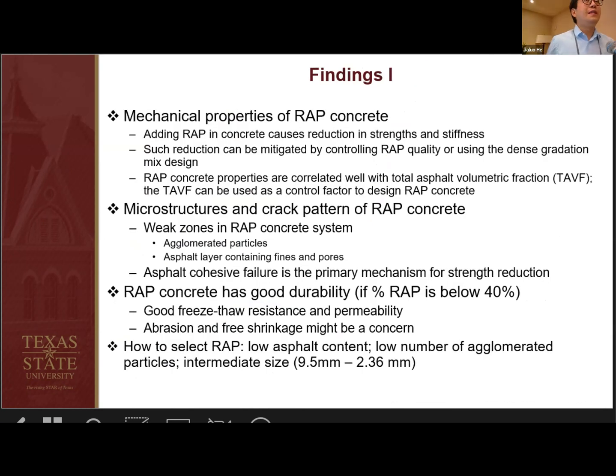Like I said, I skipped a lot of details. I just want to conclude the findings for the mechanical properties. By adding RAP in concrete, we had a reduction in strength and a reduction in stiffness. However, we were able to minimize the strength reduction by utilizing optimized aggregate gradation. And we also found the strength reduction and modulus reduction were correlated with the asphalt content. So by controlling asphalt content, you can essentially design RAP concrete with adequate strength based on your requirement.